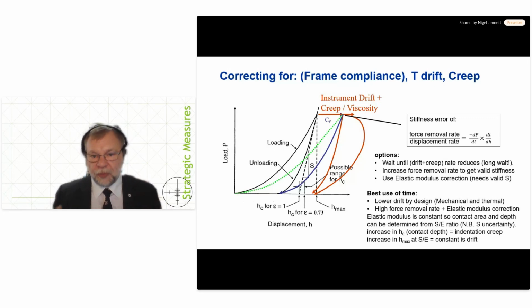However, word of warning, and the reason the Joslin and Oliver P over S squared method is not a preferred and widely used method is that, particularly for metals, which are very stiff and have a very steep unloading curve, S is very variable, and so there's a very high uncertainty in this. But it is a way forward if it's the only thing that you can do.